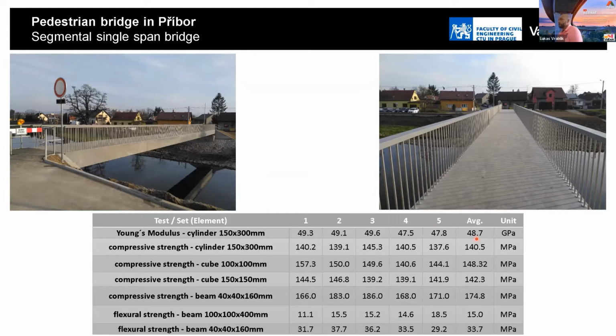But for a very small beam, with a cross-section side dimension of 40 millimeters and a length of 160 millimeters, we use it to test the compressive strength of the concrete. And for this element, we obtain a compressive strength of approximately 175 megapascal. Again, as I said, the value of the strength is affected by the dimensions and by the shape of the element used for the testing.